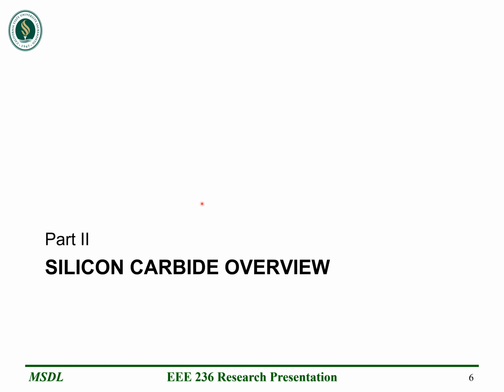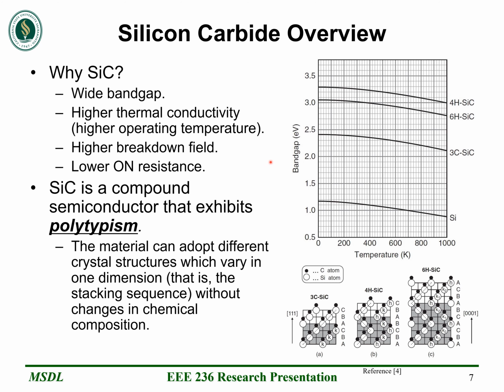Now let's dive a little deeper into silicon carbide technology specifically. So why silicon carbide? Well, there are a few advantages and disadvantages of using silicon carbide, but some of the advantages I list here. For example, silicon carbide has a wider band gap than regular silicon. It has higher thermal conductivity, which means higher operating temperature, has a higher breakdown field, and lower on resistance.